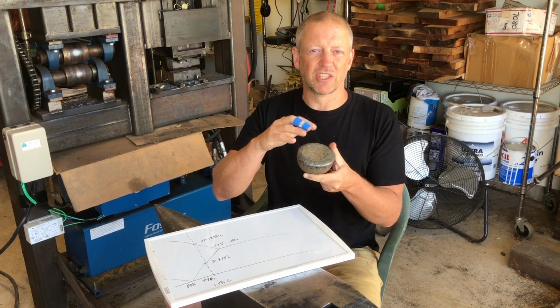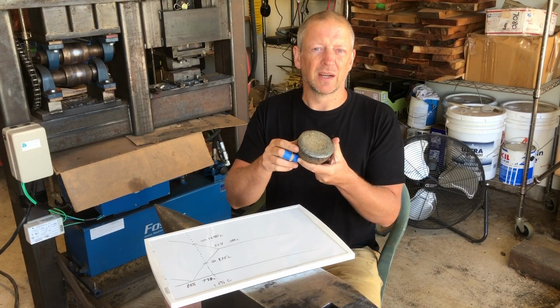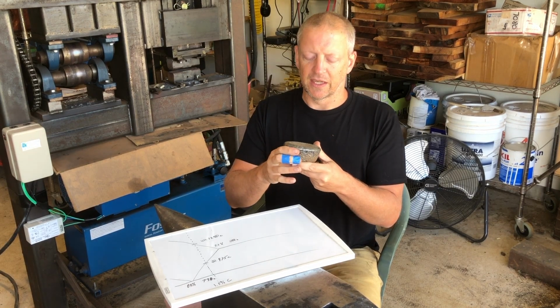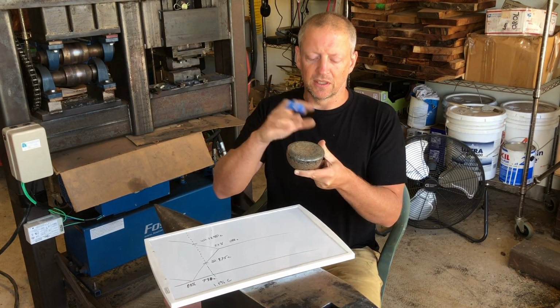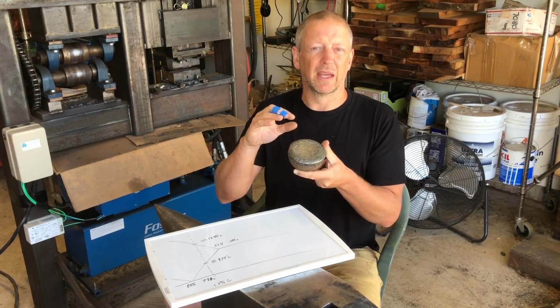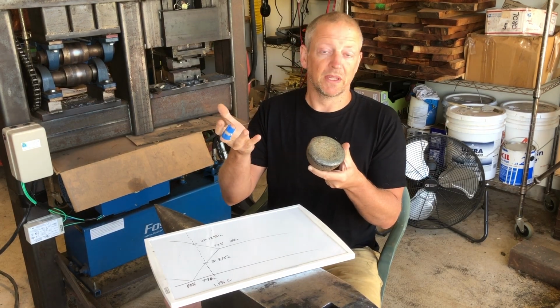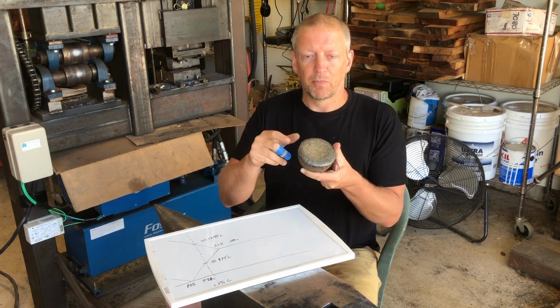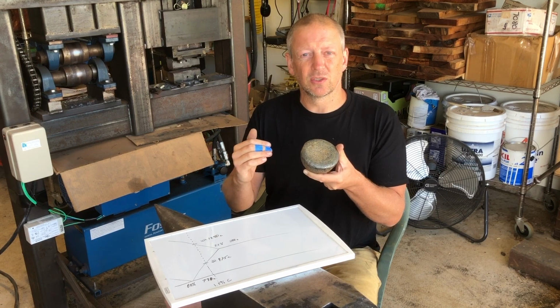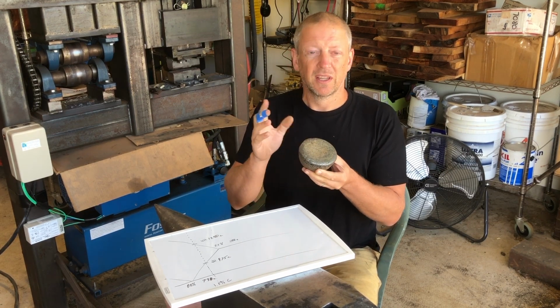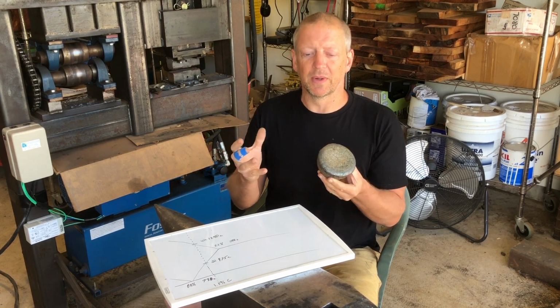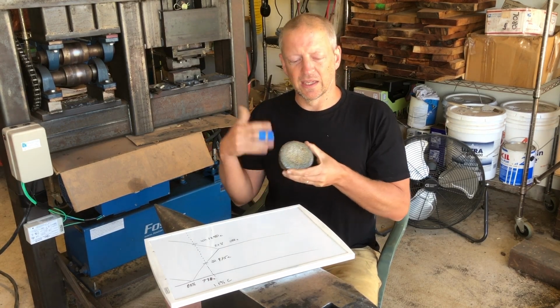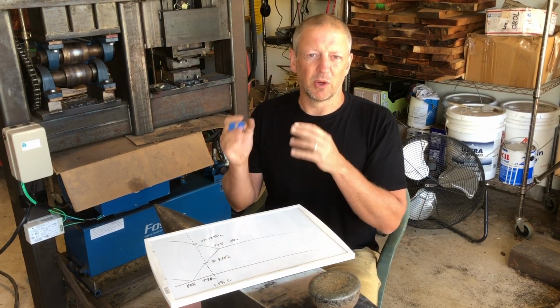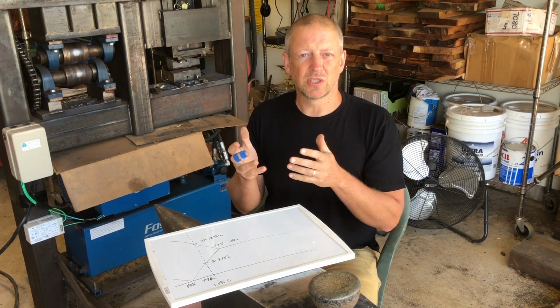Obviously on top we're going to have a dendritic structure, but just because we see a dendritic structure on the surface doesn't mean that's what we actually have inside. This is a case of that initial solidification structure can be dendritic, or will be dendritic pretty much, but during the cooling after the solidification, things can change, even before we get to any follow-up treatments. And probably the most key follow-up treatment is soaking the ingot.